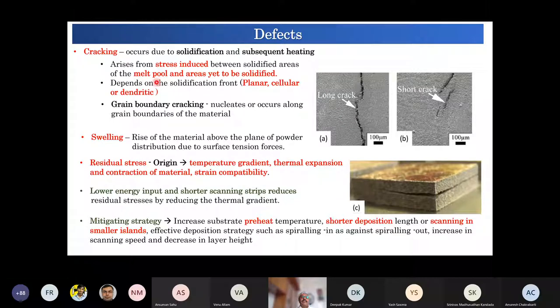So these arise from the stresses induced between solidified areas of the melt pool and areas yet to be solidified, right? Grain boundary cracking can take place because the two different regions where it is melting and growing converge, and then it can lead to some kind of cracking because there is a chemical segregation around this. So this kind of crack is quite often seen in additively manufactured materials. Then there is a swelling that happens because of surface tension forces.